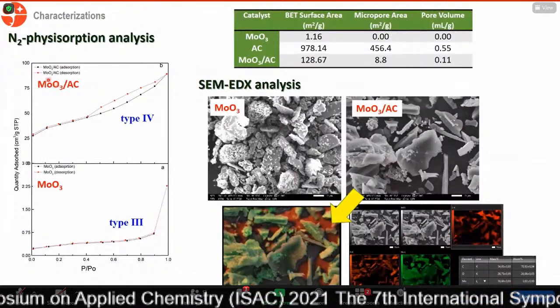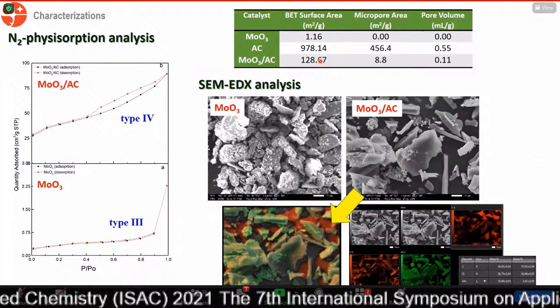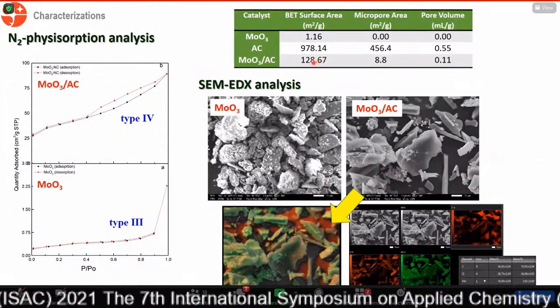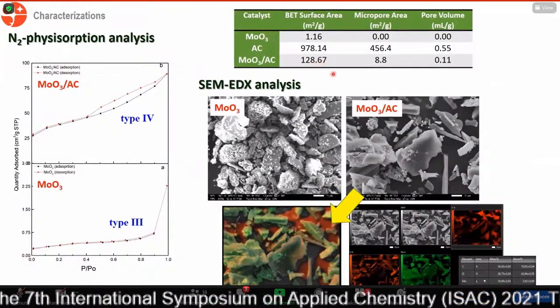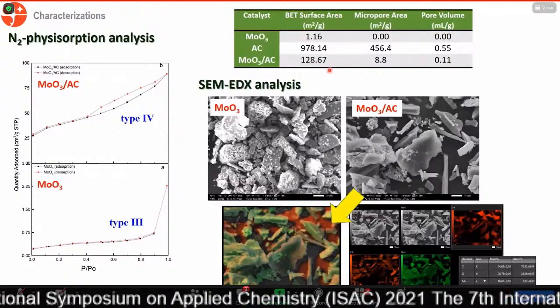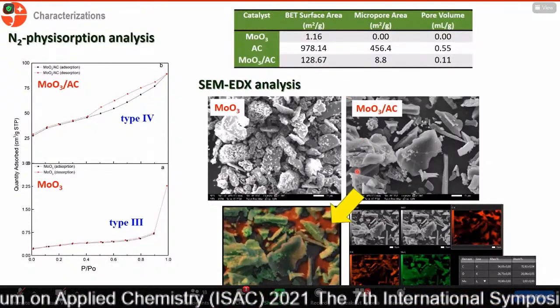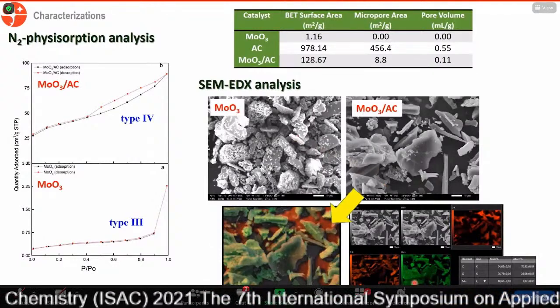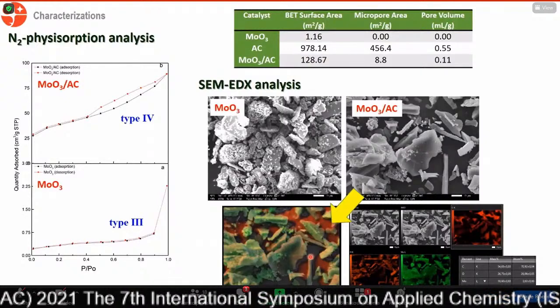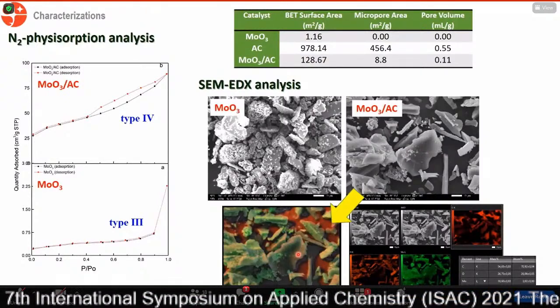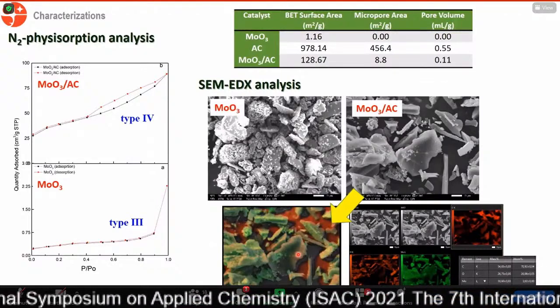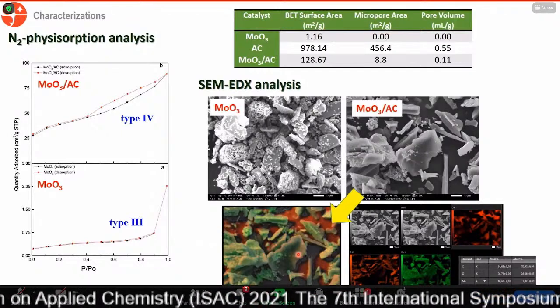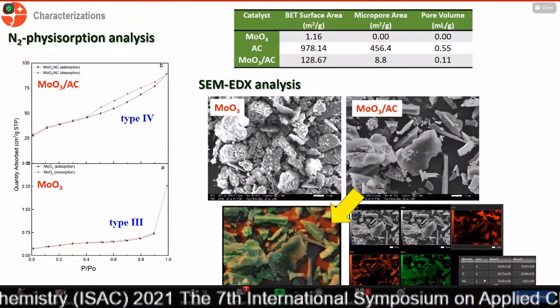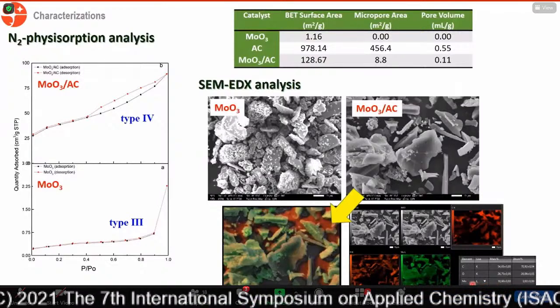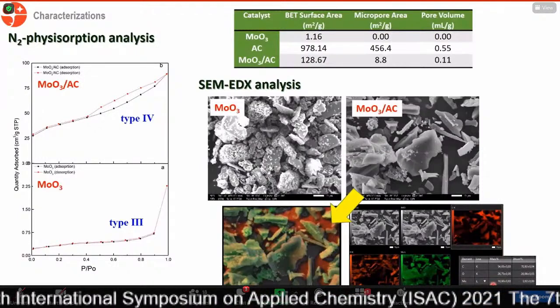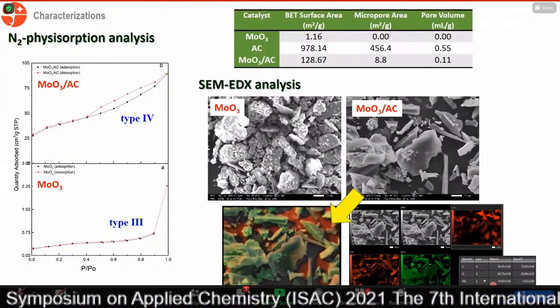However, our molybdenum oxide on activated carbon shows much higher surface area. It's about 100 times higher than the bulk molybdenum oxide. And we believe that this kind of property is very important for our reaction. As we can see here from SEM analysis, the molybdenum was well dispersed on the surface of our activated carbon, and it is not clear how big the size of molybdenum oxide on our activated carbon is. From our EDS analysis, we can see here the amount of molybdenum is quite similar to the theoretical loading of the molybdenum, which is around 18%.